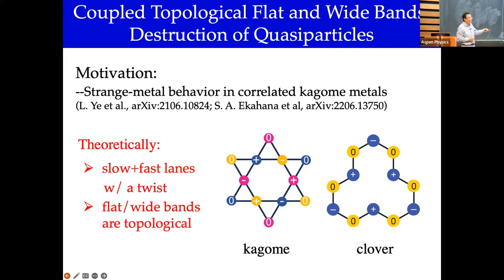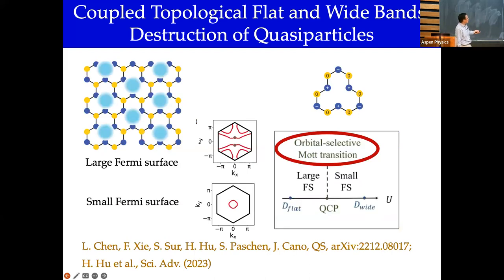And that's actually not a precise statement. Now we can do Wannier function constructions to make these precise, but the quantitative physics is that the compact local states almost act like atomic F electrons in the sense that they cannot readily move along. And so we take advantage of this recognition of these compact local states. These are molecular orbitals which cannot move along very easily. And then the other orthogonal molecular orbitals move along with very fast regular conduction electron speed. And lo and behold, even though it has no atomic F electrons, we end up with the same model, the Kondo lattice model. Some topological, and we can solve it, show this kind of large Fermi surface to small Fermi surface quantum phase transition that's continuous, and therefore a critical point arises.